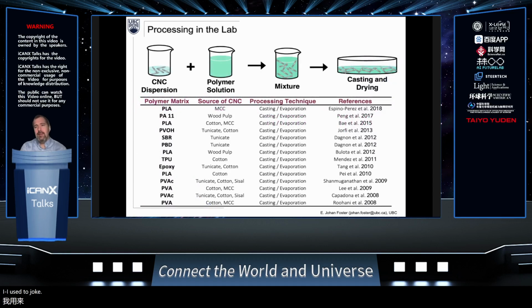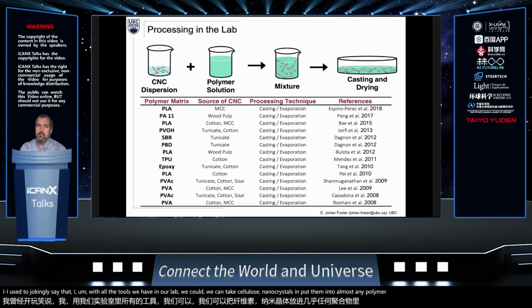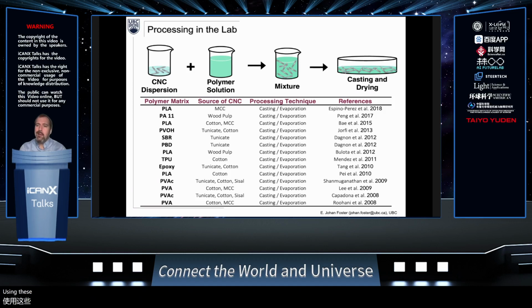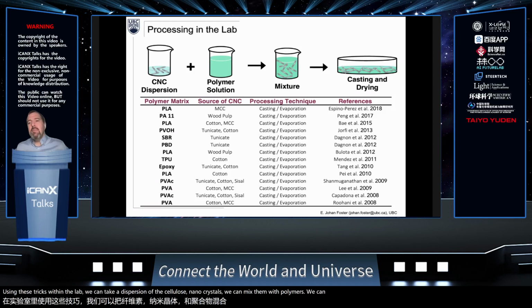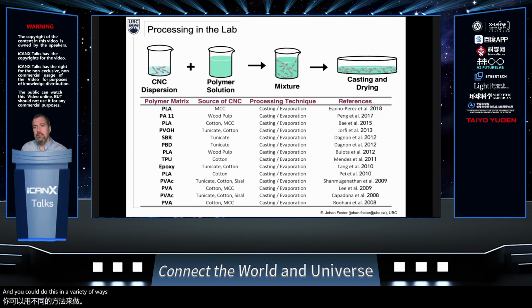I used to jokingly say that with all of the tools we have in our lab, we can take cellulose nanocrystals and put them into almost any polymer. Using these tricks within the lab, we can take a dispersion of the cellulose nanocrystals, mix them with polymers, and make a film or make a foam. You could do this in a variety of ways, but easiest inside of the lab is mixing those solvents together and evaporating it. The problem with that is that making it any bigger, so scaling it up industrially, is not very viable. Using all that solvent is slow and very costly. So what can we do?